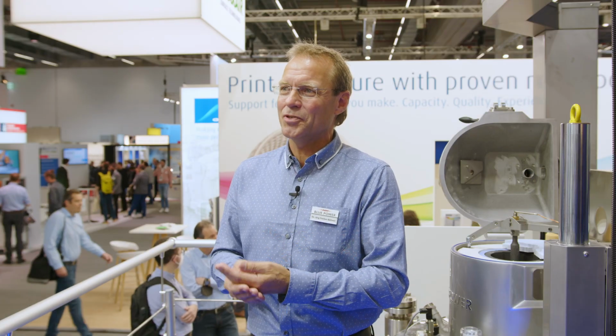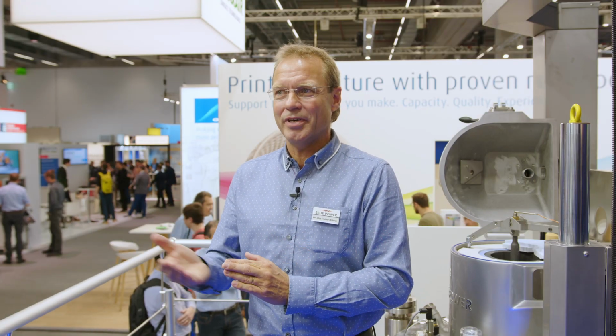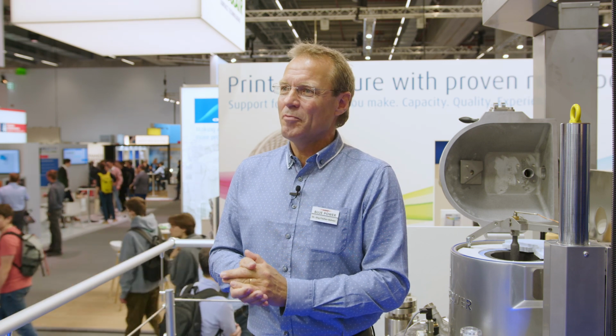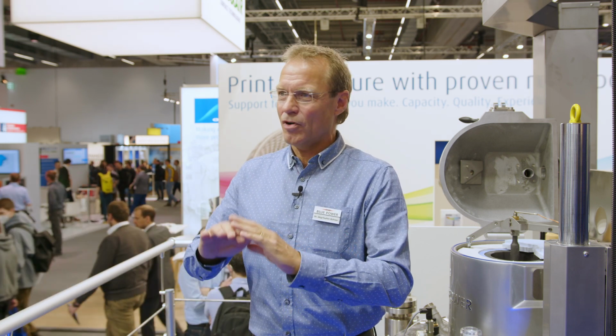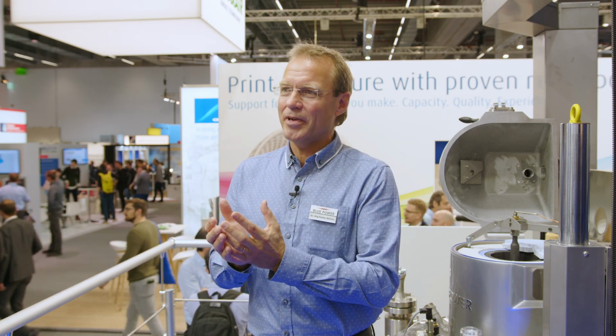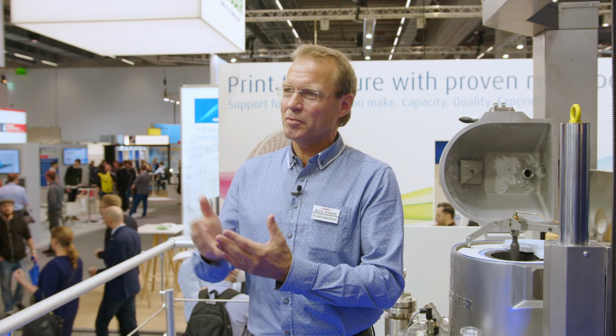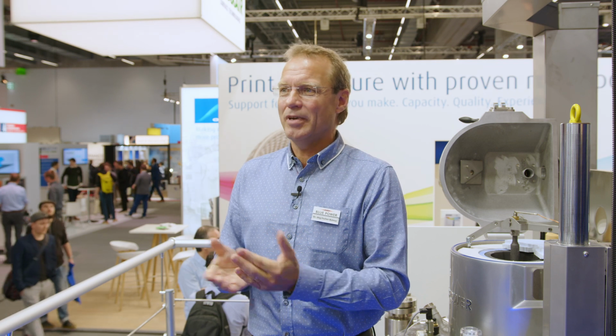The oversize and undersize that you remove from an atomized batch by sieving and classification processes, this powder can be remelted and reused. Of course, you have to pay attention to the contamination, you have to do your analysis on the powder, but it's potentially possible because all the process steps are carried out under protective atmosphere, so the amount of contamination by oxidation is limited.